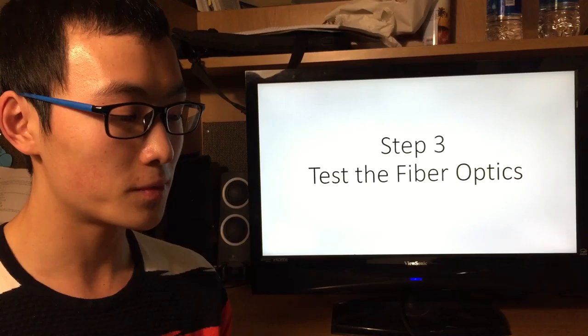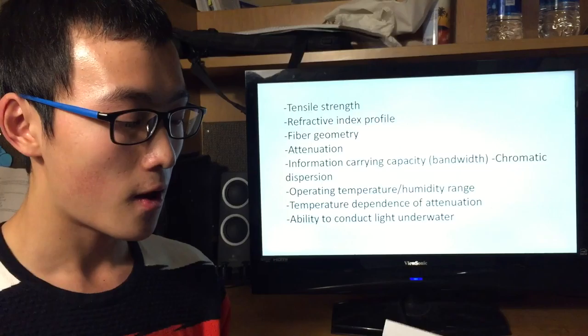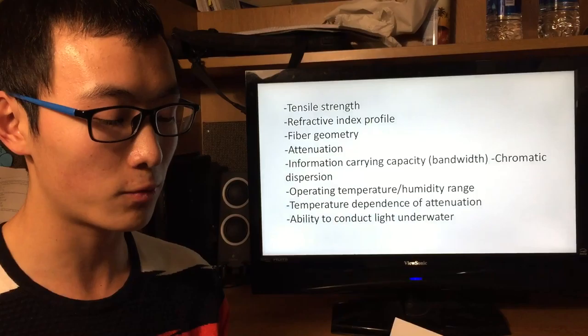Step three is to test the fiber optics. The completed optical fiber must undergo a number of tests to determine the quality of the finished product. Here are some assessments including tensile strength, refractive index profile, fiber geometry, attenuation, information carrying capacity or bandwidth.